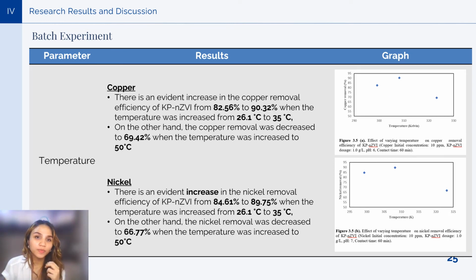The last process parameter to be observed is temperature. There's an evident increase in the copper removal efficiency of KPNCVI from 82.56% to 90.32% when the temperature is increased from 26.1 to 35 degrees Celsius. The removal efficiency is 69.42% when the temperature is increased to 50 degrees Celsius.